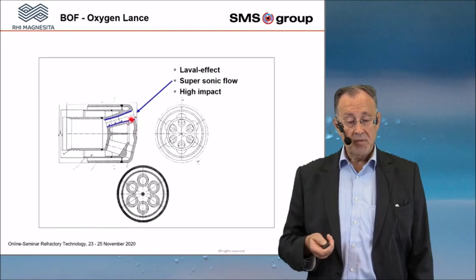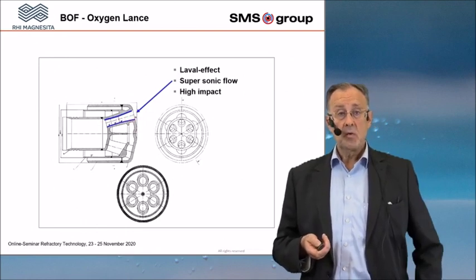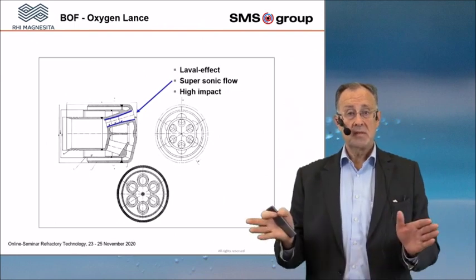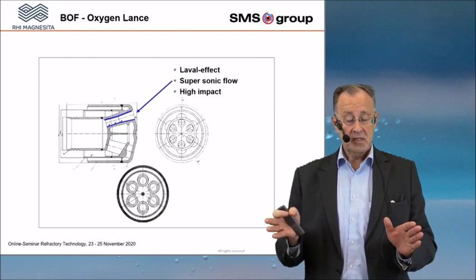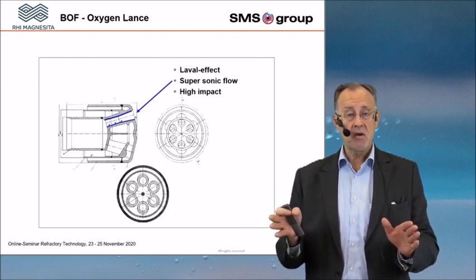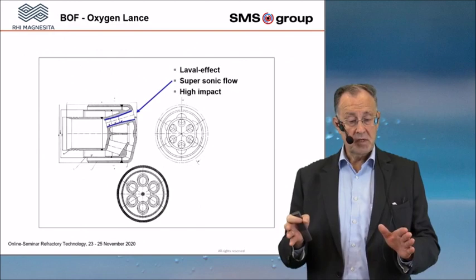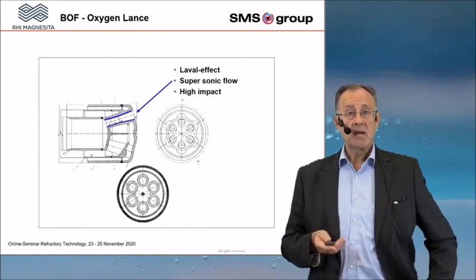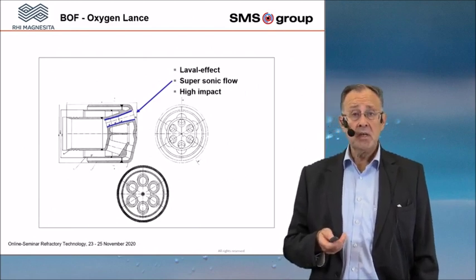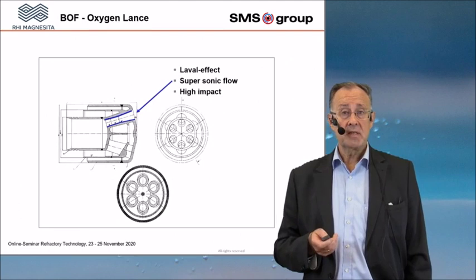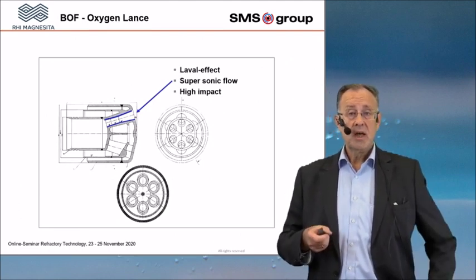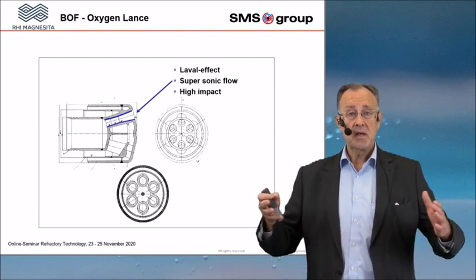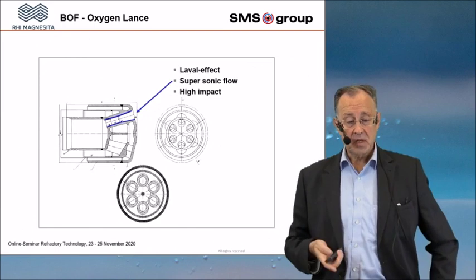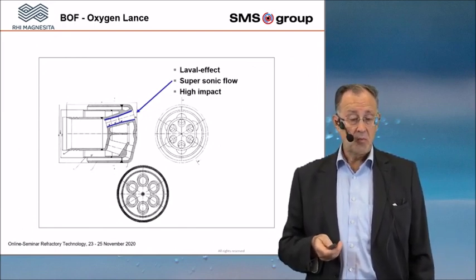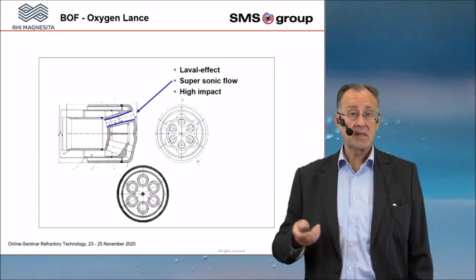The angle of the nozzles is different too. So that means they are not straight on the surface. All the tips have a certain angle so that you can cover a bigger area on the surface of your converter when you blow the oxygen on the surface of the metal bath to penetrate it inside the bath. Most lance tips have an angle of 17.5 degrees. In some cases, for example at HKM, the lance tip is 23 degrees. This is really unusual, and this depends on the geometry, that means the diameter and the height of your converter vessel, and you have to find out what the best type of lance tip is to avoid any sticking of slag and skulls on your lance.